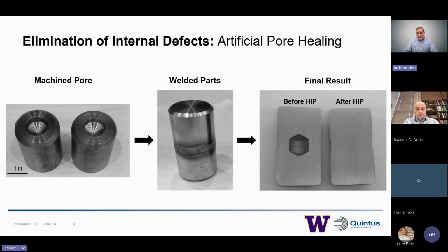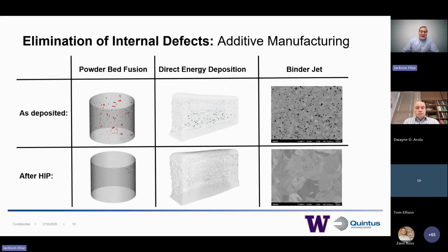The only true challenge here would just be getting that gas-tight structure in which the applied pressure medium cannot penetrate the material and allow for the pore not to be healed. If we're looking at additive manufacturing variants, we can see that powder bed fusion, DED, and binder jet all have a reduction or elimination of internal defects after HIPping. And this really provides value, as we'll see here in a second, on what it means for printing parameters if we're going to also HIP.